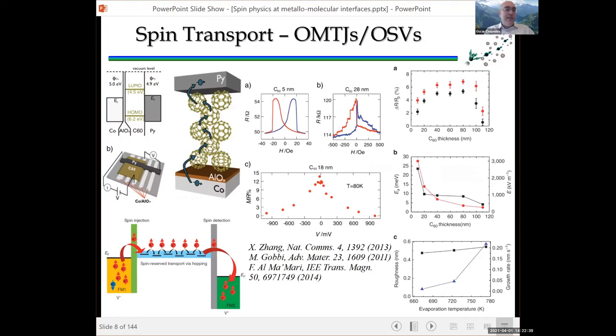But in any case, the idea there is that the LUMO of C60 is very well placed with respect to the Fermi energy of the magnetic transition metals, iron, cobalt, nickel, and their alloys. So it should be quite easy to tunnel spin polarized currents into the LUMO, the lowest unoccupied molecular orbital, for those of you new to molecular spintronics. So the equivalent of the conduction band, but localized states. And then these spins will move across the molecules via thermally activated variable range hopping. Because it's a tunneling process, hopefully most of the spins will remain polarized, and then they will undergo magnetoresistive effects on the other end of the device.